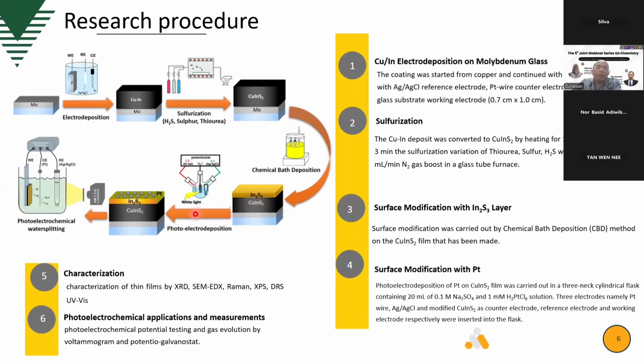After that, by photoelectrodeposition using platinum, we cover the absorber with platinum, but it will not cover all of the electrode because it would block the light. These are nanoparticles, so the light can still go through to the absorber. Then for the photocathode application, we also use three electrodes: the photocathode as working electrode, a platinum counter electrode, and a reference electrode. We give artificial light, AM 1.5, for the process of electrochemical water splitting.